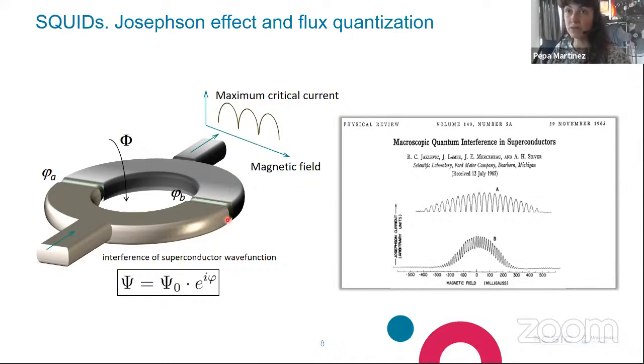This weak link can be made of any non-superconducting material, like an insulator, a normal metal, or a constriction. The Josephson effect tells us that there is a relationship between the phase difference between the phases of the two superconducting condensates and the maximal critical current flowing through the junction. As a consequence of these two phenomena, one finds a typical interference pattern of the maximal critical current that flows through the squid as a function of the applied magnetic field. That means the flux that threads this loop.